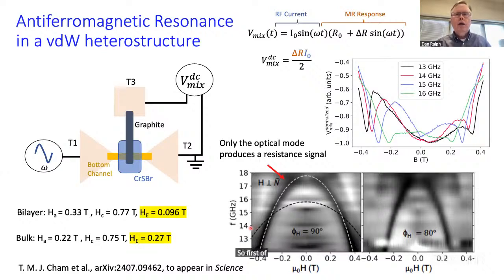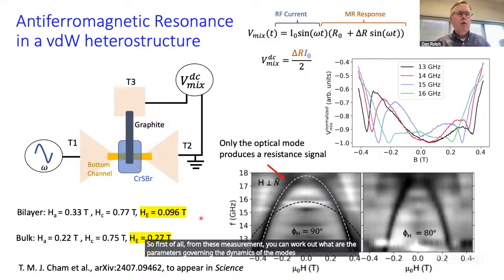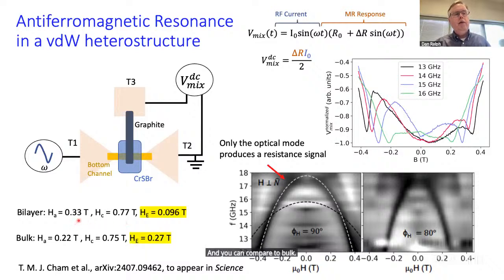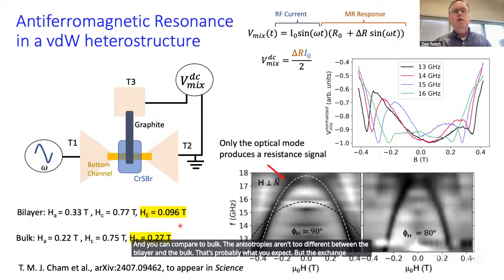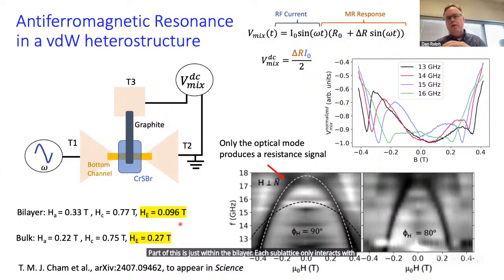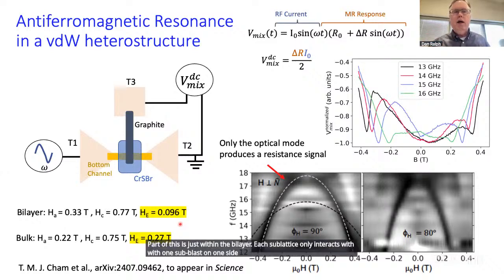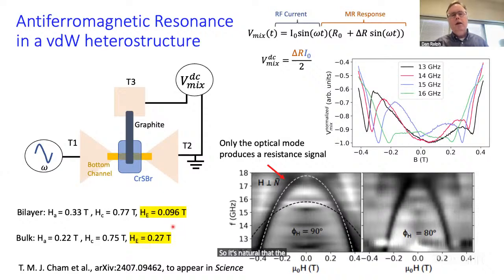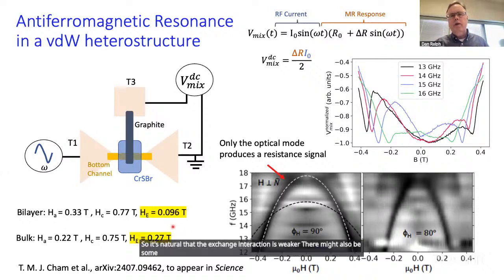So first of all, from these measurements, you can work out what are the parameters governing the dynamics of the modes. You can work out what are the anisotropy and exchange fields within this bilayer device. And you can compare to bulk. The anisotropies aren't too different between the bilayer and the bulk. That's probably what you expect. But the exchange interaction is quite a bit weaker within the bilayer compared to the bulk samples we measured previously. Part of this is just within the bilayer, each sublattice only interacts with one sublattice on one side rather than sublattices on both sides. So it's natural that the exchange interaction is weaker. There might also be some charge exchange with the electrodes that changes the magnetic properties a little bit more than that too.